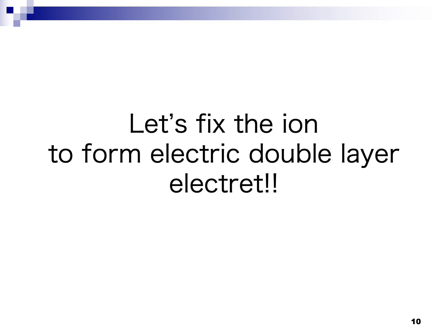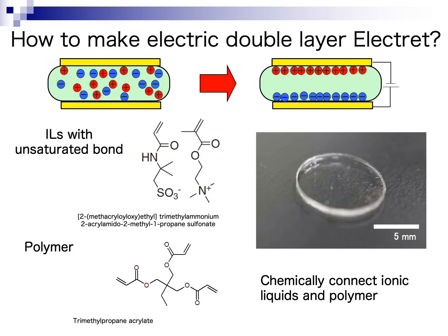To overcome these problems, we are going to introduce the electric double layer electret. So this is a picture of the electric double layer electret. In this case, we use an ionic liquid. Both the cation and the anion have an unsaturated bond, and are mixed with the polymer. And then we sandwich it with two electrodes.